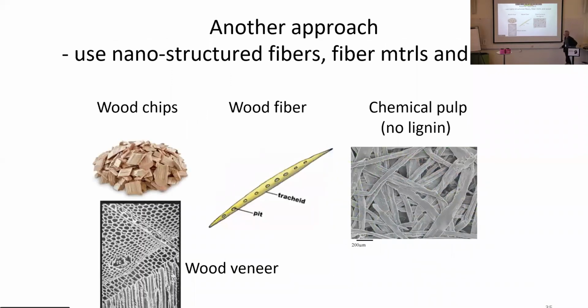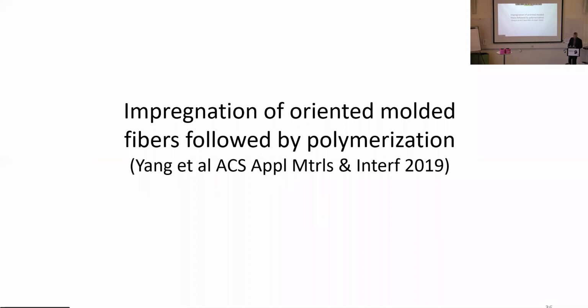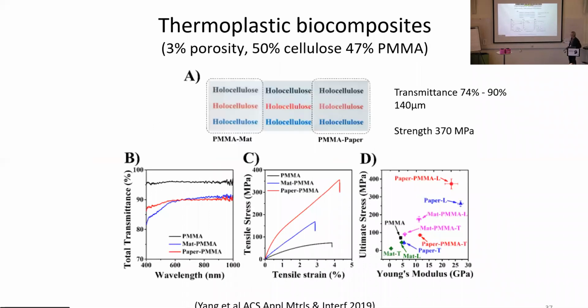Another approach is to use nanostructured fibers, fiber materials, and wood. This is what Fredrik alluded to previously. So in other words, we start with a fiber, we try to preserve the structure, but we want to utilize the fibrils which are there, and we want to preserve them as much as possible to utilize their properties. So this is data that he already showed. You take oriented molded fibers and you polymerize, and you end up with exceptional properties. So compared with anything else, we are much above, both in terms of stiffness and strength.